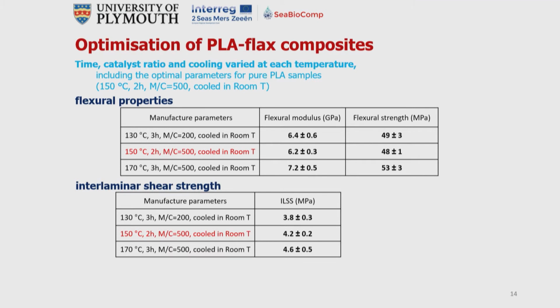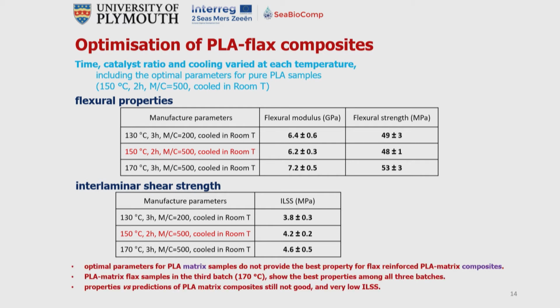So there are differences in the air that's affecting the process somehow. And again, the numbers that we've been given previously were given as the lowest interlaminar shear strengths, indicating that the fibre to matrix interface is weak. So the optimal parameters for casting resin are not the optimal parameters for making the composite.